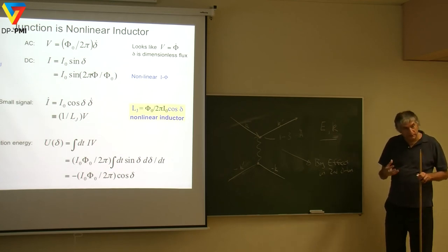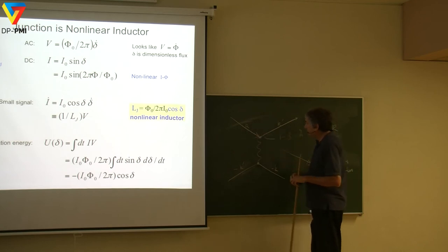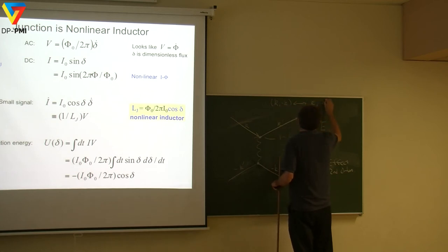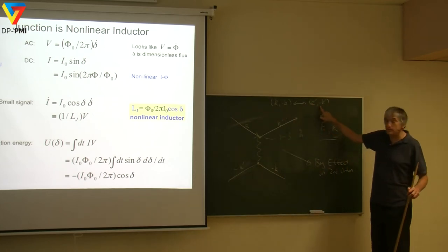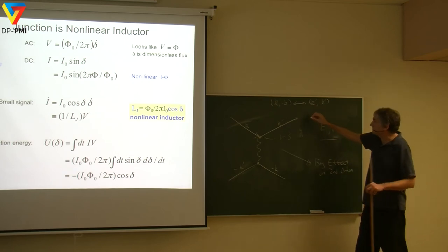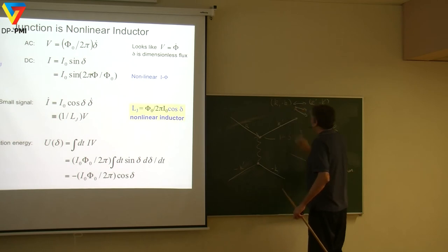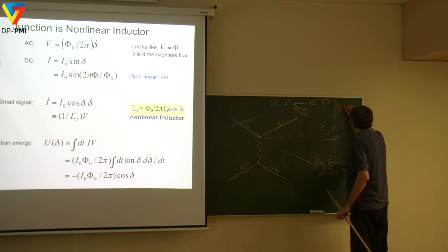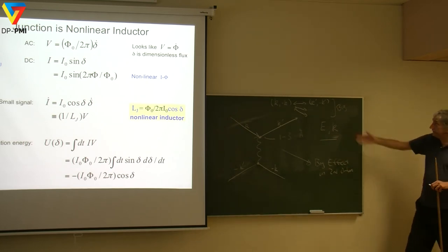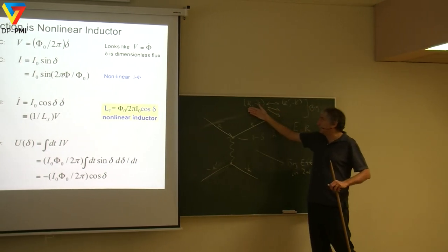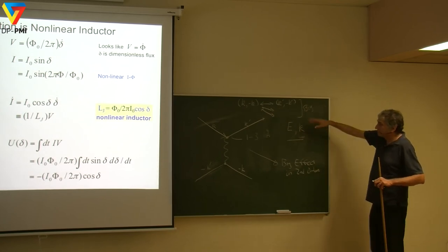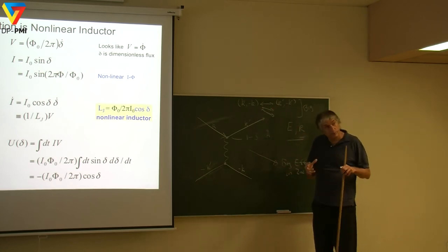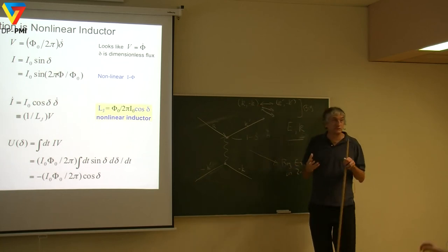And what happens is the superconducting state condenses into this state where you have electrons of K and time reverse scattering back and forth to K prime and minus K prime. Happens all the time. And there's a huge number of states here, right? There's a huge number of electron states. This is huge. And this is scattering to all these other pairs of states. And they're all scattering coherently in the same way. So you can have a big effect because it's scattering back and forth. So these states here are called the Cooper pair states of momentum K and minus K, of time reverse states. And they're all scattering from each other. And because all these states are the same, they have zero momentum, you can do a Bose condensation because all these states are essentially a zero momentum state.